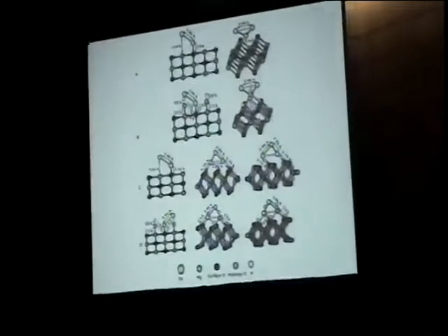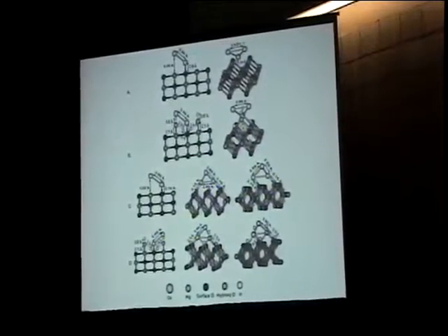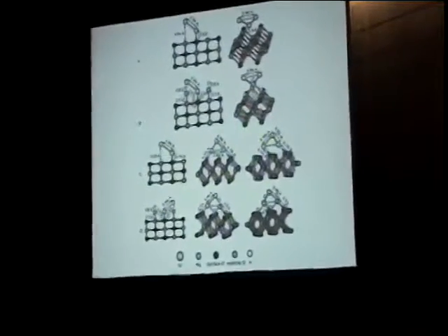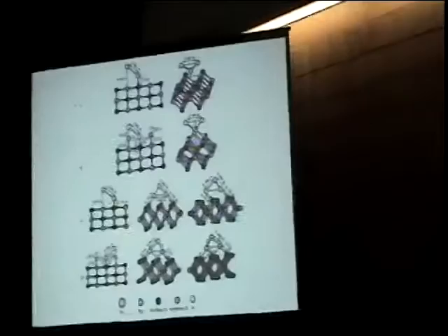And the triangles you saw were isosceles, so they're not planar, they're not perpendicular to the beam. So it becomes a geometry problem, but one can figure it out. The only way the osmiums are atop the magnesiums is if the clusters are tilted with respect to the plane perpendicular to the beam, and the tilt angle turns out to be 38 degrees.